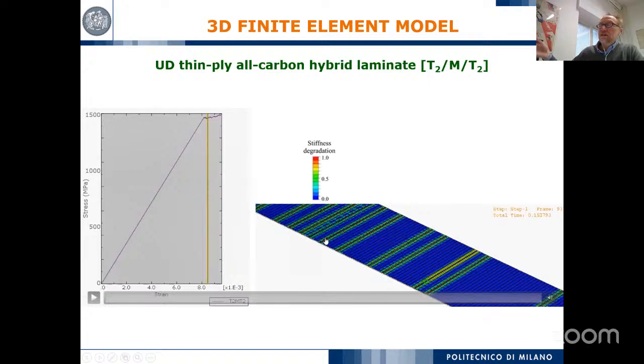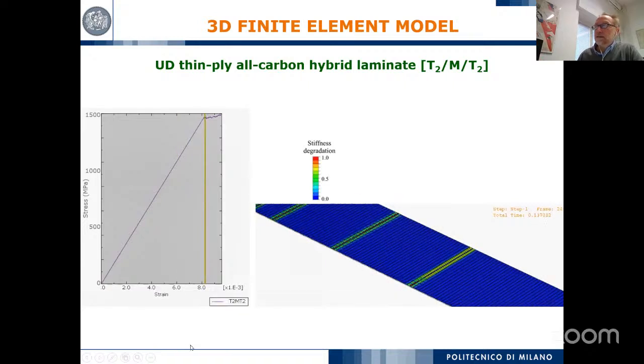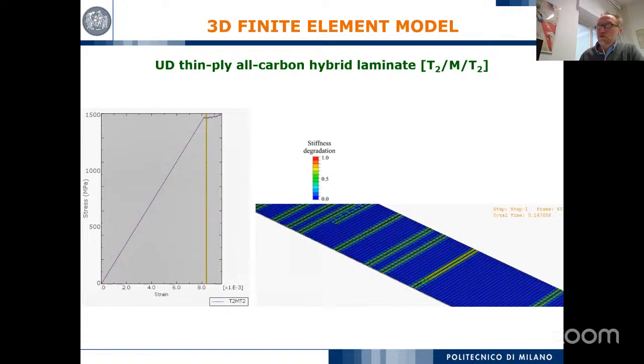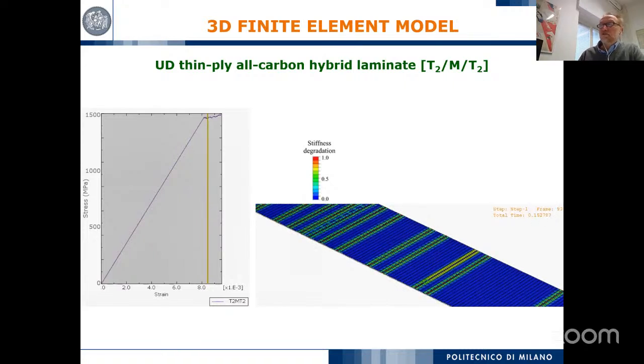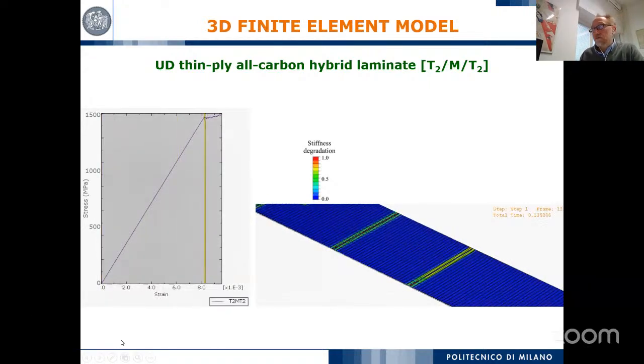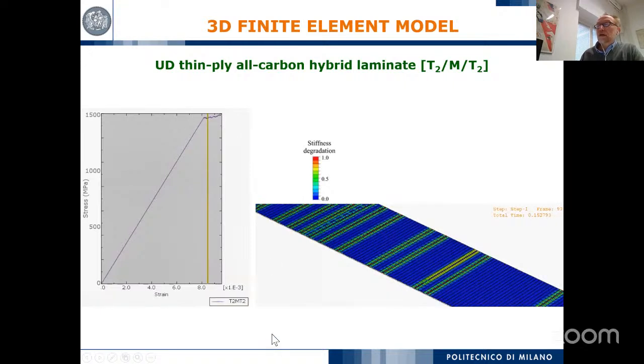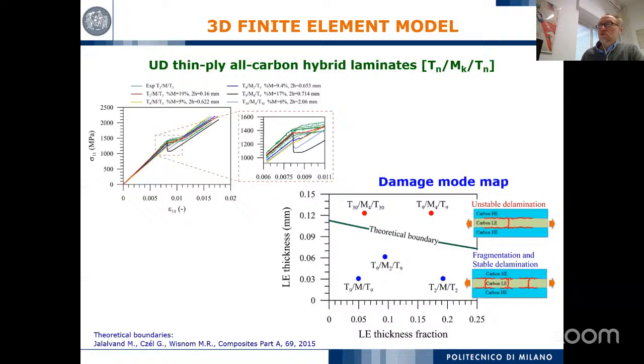Then you see that this is mainly fragmentation. You have several fragmentations that appear in the material at different positions, and this is mainly due to the Weibull distribution. This is limited to fragmentation with a very small extension of the delamination, which is limited to the position of the fragmentation. And this is what has been observed in the experiment and is the motivation for the plateau. Moving to an extended number of simulations: once we know that the simulation provides good results, that is, we can trust the results, we can extend this simulation